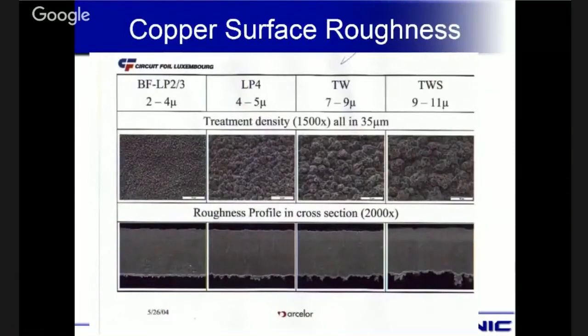So, on this next picture, if you look at the bottom pictures, right at the bottom, you can see there's a tooth, and this is how we typically stick the copper to a material, and this is true on FR4, polyimide glass, and Teflon materials. We are relying on this tooth on the bottom of the copper to grab into the dielectric material, and that's how you get a bond. So there's no glues involved. In our situation with the Teflon, we're taking our Teflon materials up to about 900 degrees Fahrenheit, melting the Teflon, and under very high pressure, melting the Teflon into the copper surface. So we're relying on this tooth in a lot of ways to make sure that we get good adhesion.